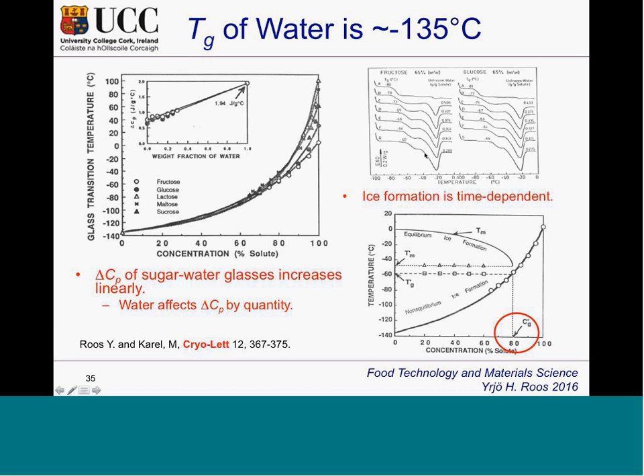We can do that and show that what we were looking at as Tm prime and Tg prime were actually validated. Also, if we look at the glass transition temperature of water, we have publications that show it at around minus 135 Celsius. And these data show that that's where it tends to go if we have the heat capacity measured and published for unfrozen water. So the area of water glass transition is very complex, and there's a lot published on that.